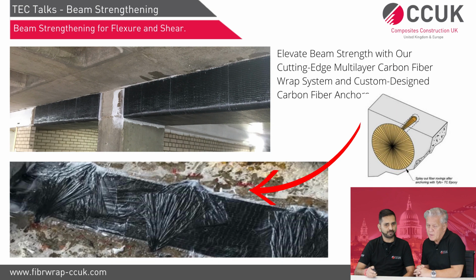I think just going back to what we were saying about the headroom, with carbon fibre being so thin, architects really do prefer using it because they can save a lot of space. It is, yeah. So in that particular project as well, the architect was very keen to use carbon fibre because the other solution was to put new steel beams underneath, which was, as I said, reducing the headroom, changing the profile completely, and also adding dead load onto the structure, which was becoming difficult for the structural engineer. So for that reason, FRP was preferred.